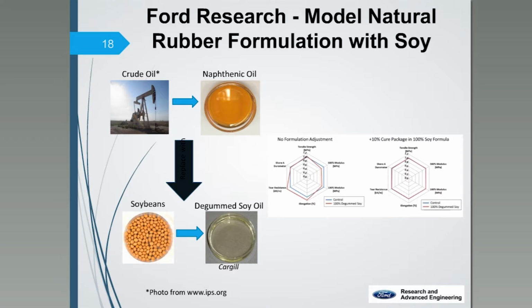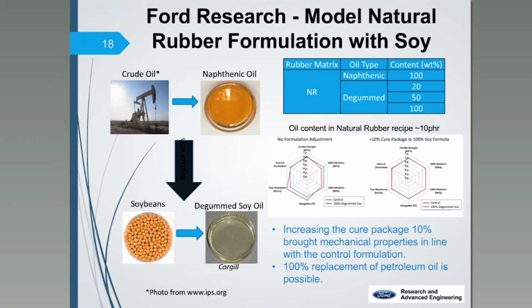With work in the laboratory, we found a way to modify what we call the cure package, that would be the level of the sulfur and the accelerators, to bring the mechanical properties back in line, or the physical properties back in line with the control formulation. So we found that, yes, 100% replacement of the petroleum oil is indeed possible. We tested it at 20, 50, and 100% replacement.